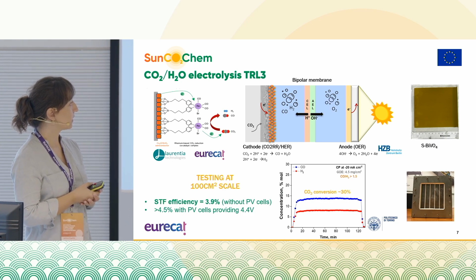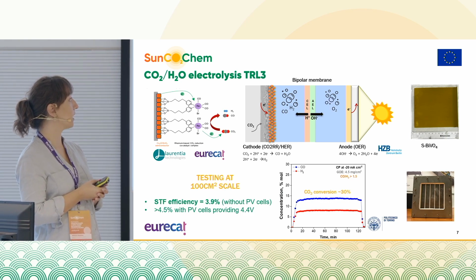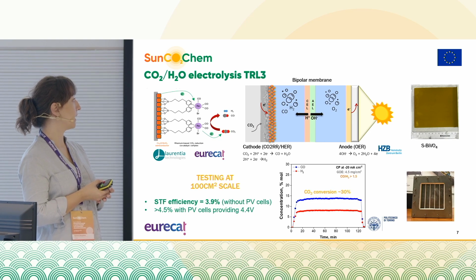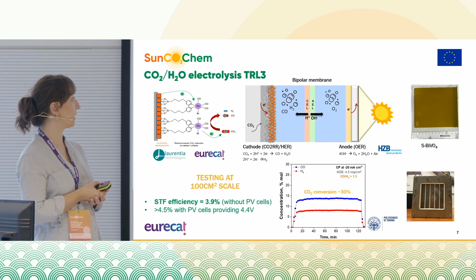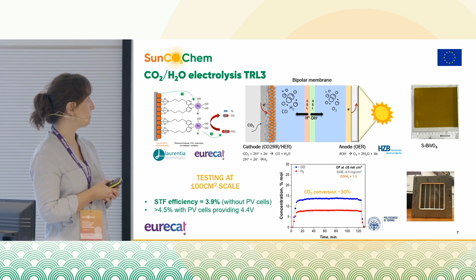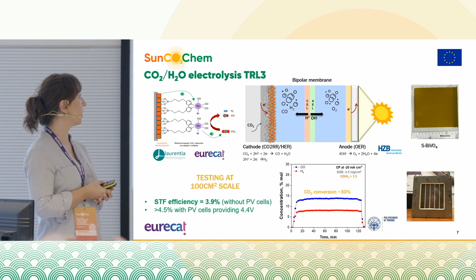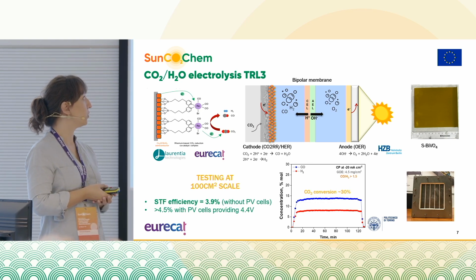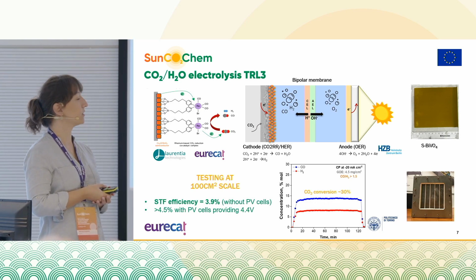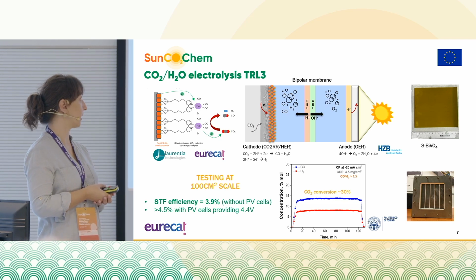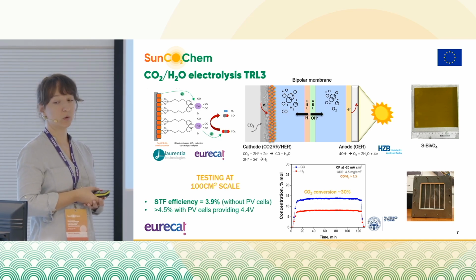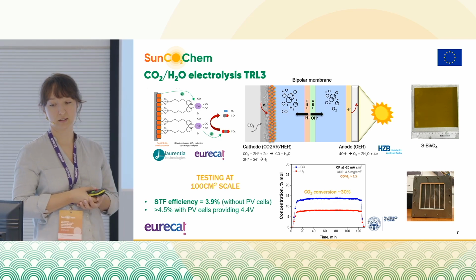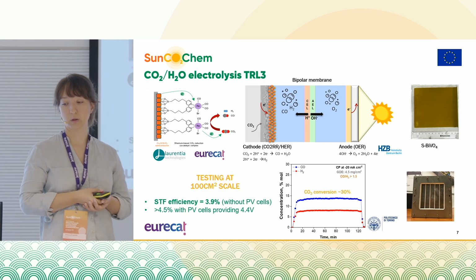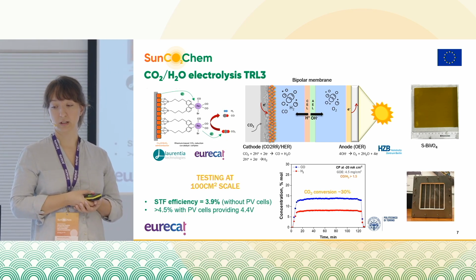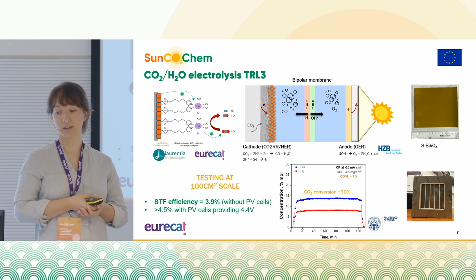The hydroxide ions are oxidized on the photoanode made out of bismuth vanadate to oxygen, while protons, together with CO2, are being reduced to hydrogen and CO, respectively, on the cathode. For the cathode material, we use copper oxide tin oxide based semiconductor and coordinated to it a rhenium-based co-catalyst.